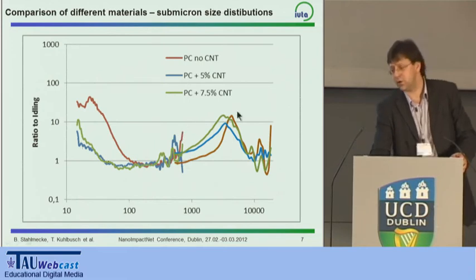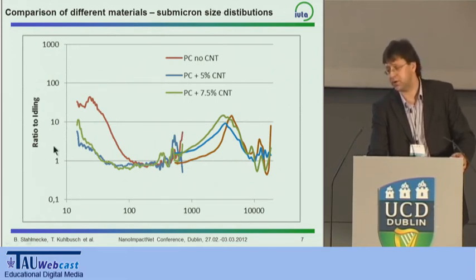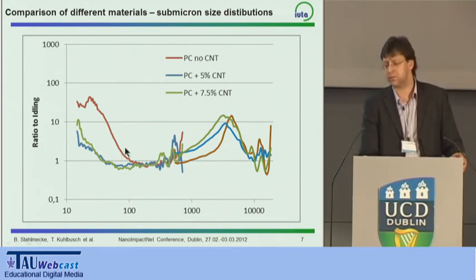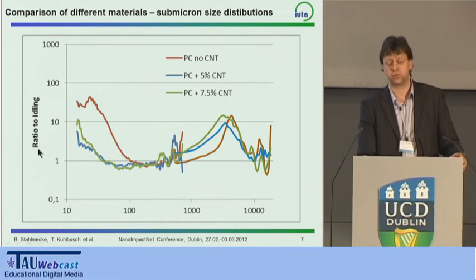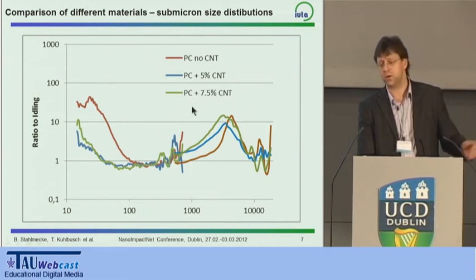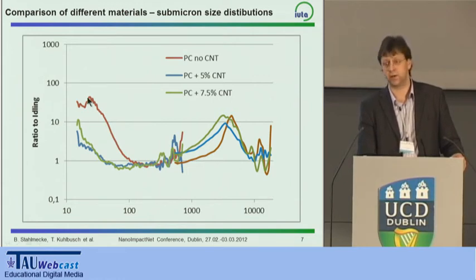So coming here, you see the overlap. This was the range measured by the APS system, and this is the range measured by the SMPS system, and it is always a reporting of the number concentration in ratio to the idling concentration. What can be nicely seen is that we have 2 modes, whether we have the polycarbonate with no CNT or with CNTs, both modes are visible. One is a mode below 50 nanometers coming from the process, and one mode is in the size range above 1 micrometer. It's quite interesting to see that this is not coming from the idling, so it shouldn't be just the engine in idling mode, but that something is actually released by the shredding process itself in the nanosize range.